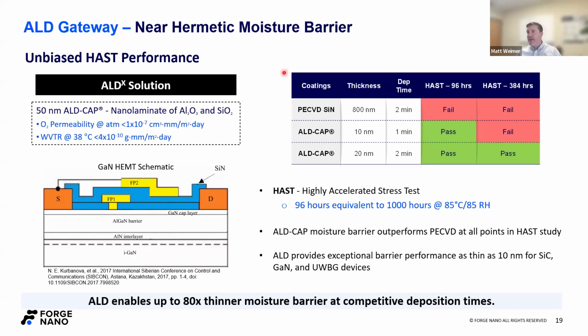The second thing I love to talk about is this comparison with PECVD. So we had a customer that had an existing silicon nitride PECVD moisture barrier of 800 nanometers. They couldn't get it to pass their accelerated testing requirements. In this case, they actually needed to get to 384 hours at 85 C and 85% relative humidity. So we said, hey, let's see what thickness we can get done with the ALD cap solution. At 10 nanometers, we were actually able to pass 96 hours at HAST. So if we pause there for a second and think about the implications of that, we have 80 times less film and it performs better. So yeah, ALD is slower, but if you only need 1/80th or heck, even 1/50th the film, you're not really losing that much time.